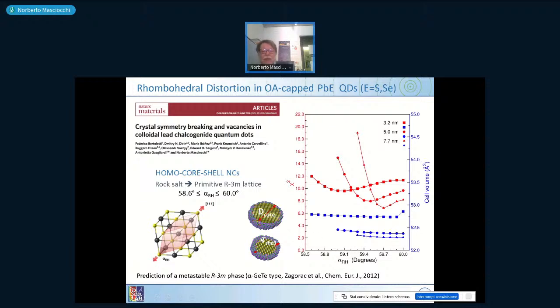This is given by the fact that the shell becomes more and more important when you are shrinking down the size to a small system. So the expansion of the cell, which is typical for the 3.2 nanometers, the number of atoms which are in a shell compared to the ones who are in a center part becomes comparable. And then you have a definite widening of the cell volume.